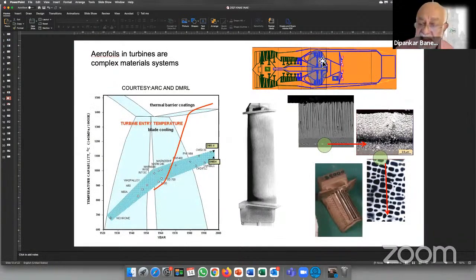The materials in the turbine are complex material systems. The turbine entry temperature in today's aero engines is actually much higher than the melting point of the nickel-based superalloy that is used as the material. And this is made possible by casting hollow blades, which allows internal cooling airflow through the blades. It is made possible by oxidation-resistant coatings on the blade's surface and above the oxidation-resistant coating, a thermally insulating ceramic coating. And therefore, this is actually a material system.